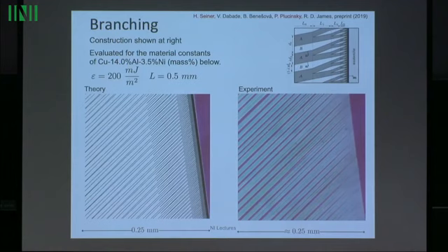The role of the branched microstructure is that you remove the transition layer. The transition layer that we originally constructed here gets delocalized. So the elastic energy is over a much larger region, but still the predictions of volume fraction and the normal of the interface are the same.